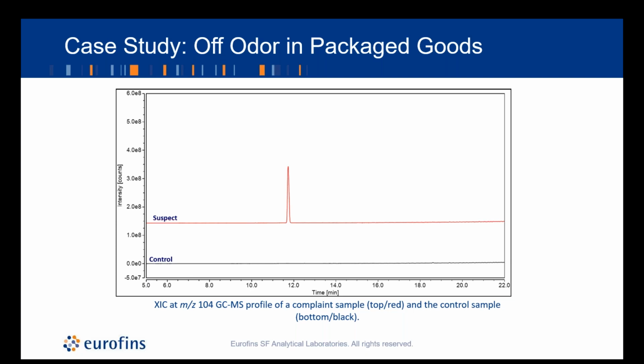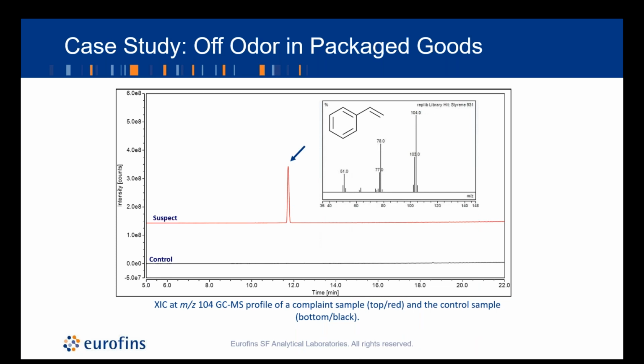In our TIC, we noticed a peak around 12 minutes, and this was identified using our mass spectrum, which is shown here, as styrene. We wanted to look for very low levels of this compound in our suspect samples, and so we produced these extracted chromatograms at a mass of 104, and that is what you're seeing here. In our control, you can see by extracting, we've cleaned up our background. We have very few other peaks, and we have our nice distinct peak identifying styrene in our suspect sample.